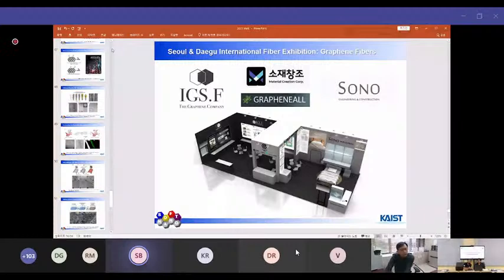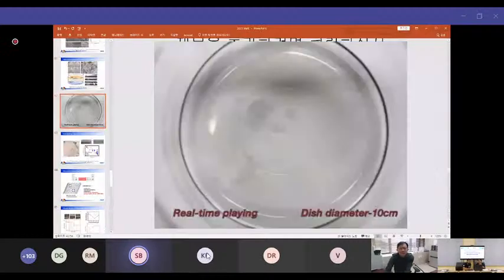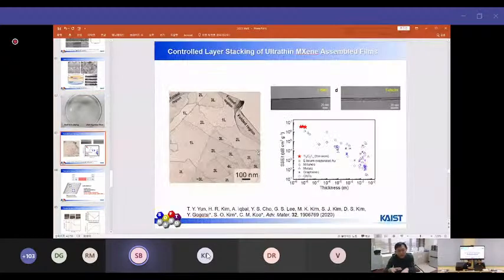Actually, the shape of the 2D material is arbitrary. It's not well defined. So there is no regular packing. But in our Marangoni effect, there is a strong Marangoni effect to have a close packing, even though each particle is irregular. So there is a minimal probability to have a void. That's the advantage of this process.